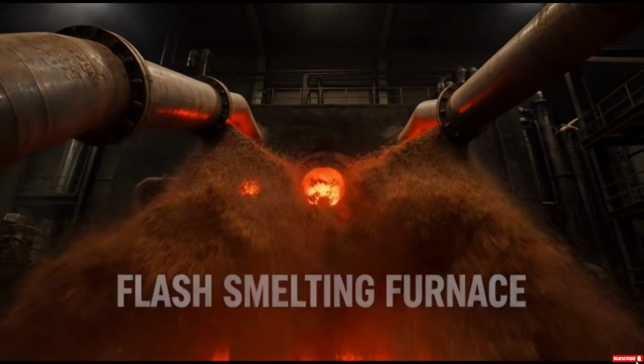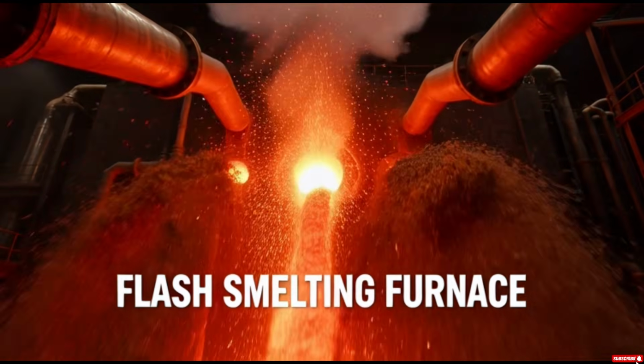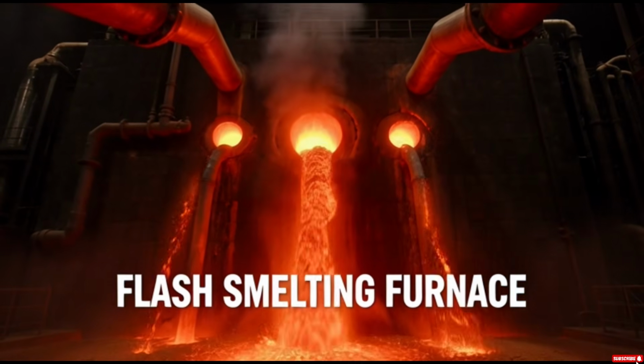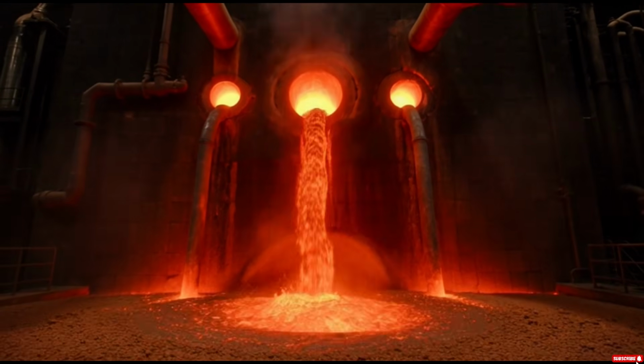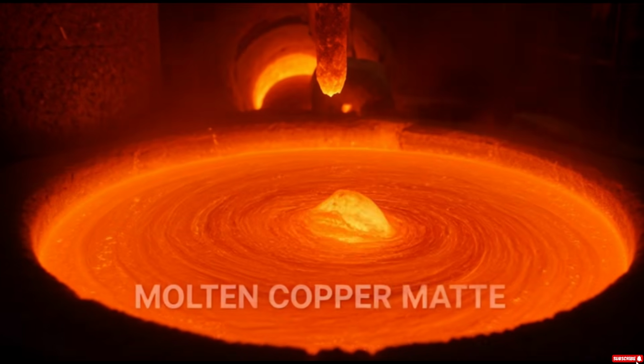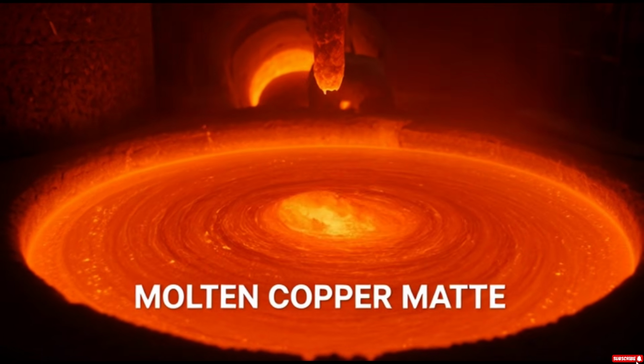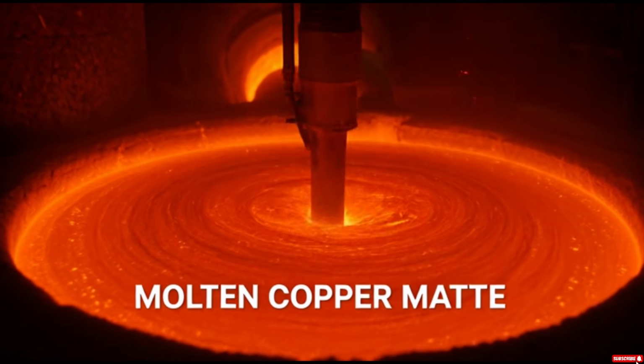Into the flash furnace, 1200 degrees Celsius. The powder melts instantly. The heavy stuff sinks. This is matte, about 60% copper. The light slag floats on top.